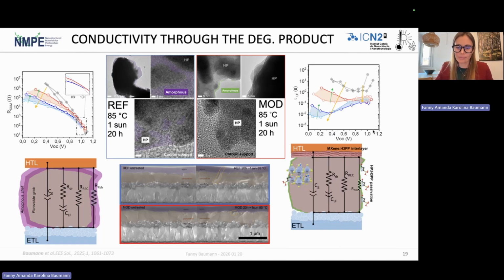So we believe that this is highly related to the conduction of ions, given that the new material that we see is very carbon rich, and a good carbon source inside the perovskite would be the organic cation.